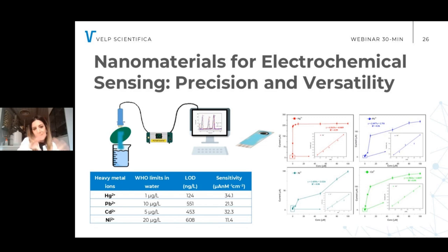The last part of the application was to develop electrochemical sensors. We use screen printed carbon electrodes, drop casting our solution onto the working electrode in order to modify it and improve the sensitivity and selectivity of the sensor. According to the response to the heavy metal ions, we also analyzed how these carbon nanodots could improve the electrochemical behavior. We reached a really interesting goal by improving the capability of this sensor, with really low limits of detection for all of these heavy metal ions, analyzed simultaneously through square wave anodic stripping voltammetry.